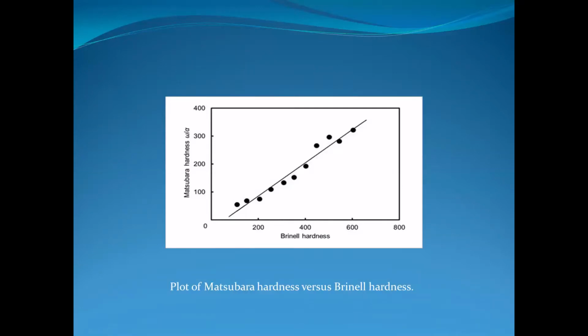The ratio omega by alpha is considered a measure of hardness. The figure shows the relationship between omega by alpha and Brinell hardness. Omega by alpha increases with increasing Brinell hardness and has a stronger tie to Brinell hardness than omega. Because the numeric value of omega by alpha is also about the same as the typical hardness value, omega by alpha is apparently a more appropriate hardness indicator than alpha or omega. The authors would like to newly define omega by alpha as the Matsubara hardness, if you agreed. It increases with working hardness, indentation hardness, and resistance to flow.